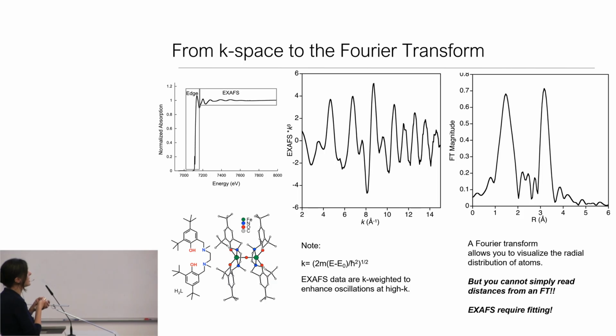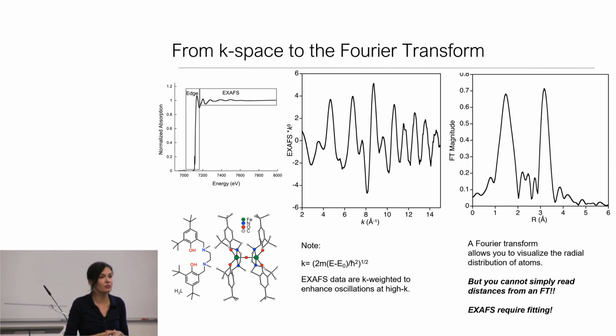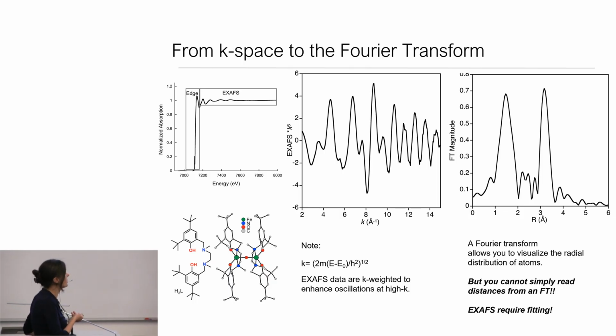One thing I want to emphasize is that these tell you there's something around 2 angstroms and there's something around 3 angstroms, but please, please, please never read a distance off a Fourier transform. You can't do that. They need to be phase shift corrected, and the phase shift correction is different for every scatterer. So you can really end up in a bad space. Also, we're only showing the magnitude here and not both the real and imaginary components. So again, just simply reading distances is misleading, and EXAFS really have to be fit.